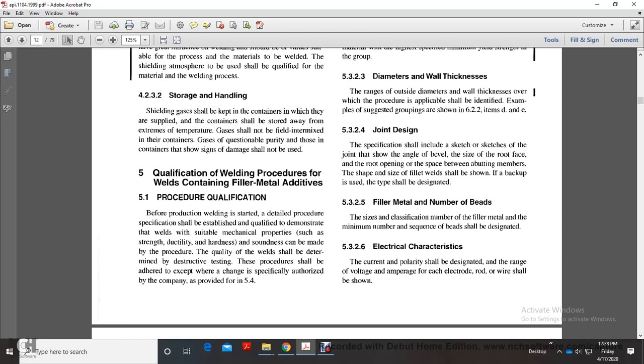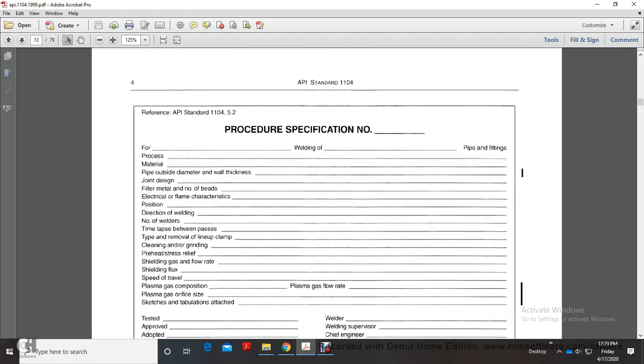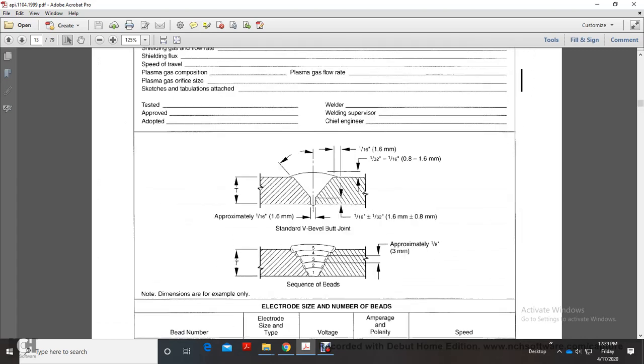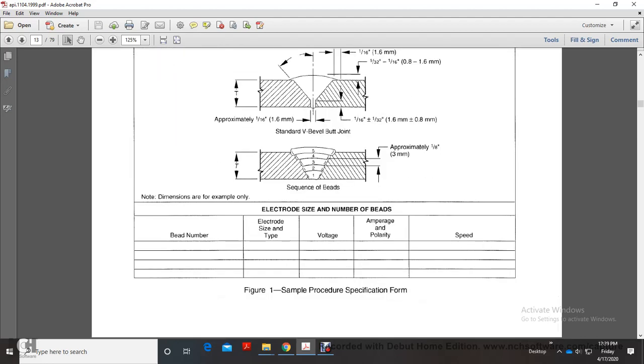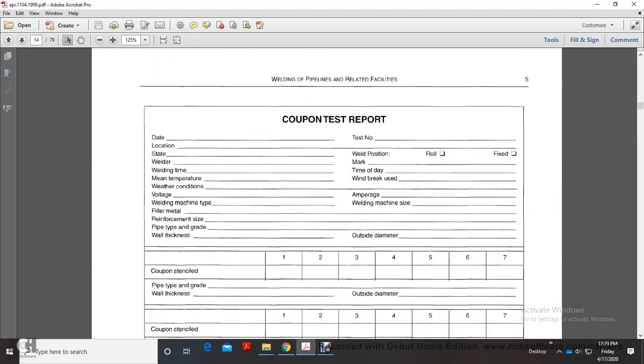5.3.2.5 Filler metal and number of beads. The size and classification of the filler metal and the minimum number and sequence of beads shall be designated. 5.3.2.6 Electrical characteristics. Current and polarity shall be designated, and the range of voltage and amperage for each electrode, rod, or wire shall be shown. It shows the procedure specification, then the sequence of beads, standard V butt joint, electrode size and number of beads, and the coupon test report.